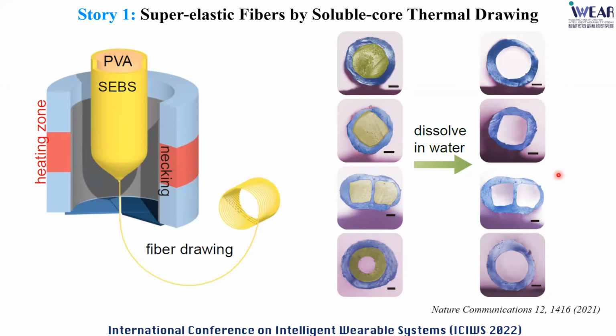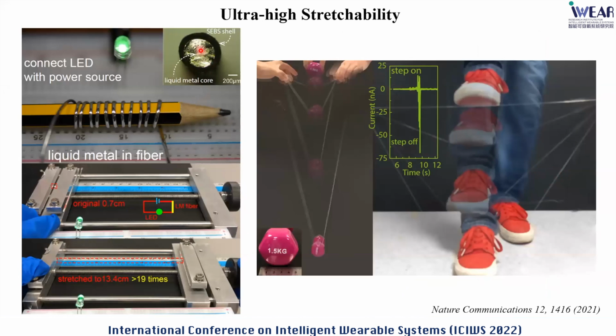After fabrication, we infiltrate the liquid metals into those cores. And we have demonstrated, for example, when we stretch those fibers over 19 times, it's still electrically conductive. And more interestingly, when we test the mechanical property of those materials, for example, here we have a piece of fiber, and we drop a 1.5 kg weight, and this fiber was extremely stretched, but the performance was also maintained.